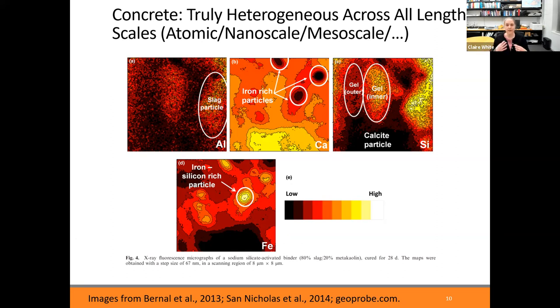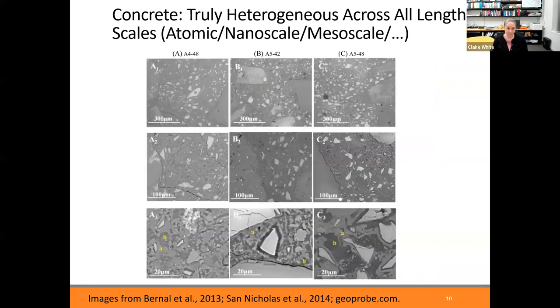And so this is X-ray fluorescence data of alkali-activated slag. And you can see here, we've circled an unreacted slag particle. There's also these iron-rich particles that are there. The gel's forming, but the gel isn't uniform. There's different compositions. And this is only 8 microns in size. So there's a lot of heterogeneities even at the micron length scale.